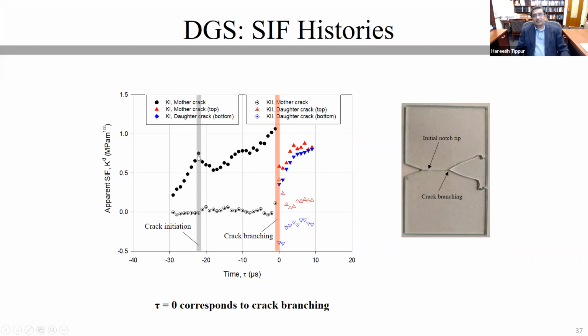Due to initiation at the notch, the crack unloads a little bit, and then begins to ramp up again, and builds up to approximately twice the value of this low stress intensity factor. The value of around 0.55, 0.6 increases to about 1.1, 1.2 megapascal root meter, and then branches. When it branches, it drops down to approximately the same value where it was at the low point in the case of the mother crack, and the values continue to increase.